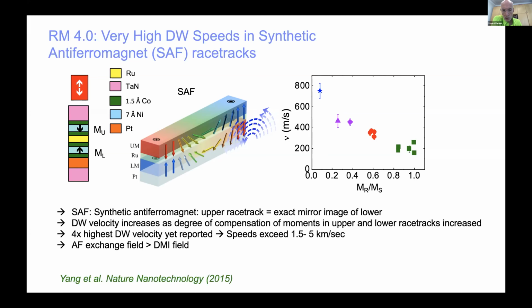ferromagnetic layer. So the cartoon shows you a domain wall. And the point here is that these domain walls, I didn't mention, this platinum layer provides another very interesting aspect, which has been discussed before, which is that it gives rise to a Dzyaloshinskii-Moriya interface exchange, a vector exchange. And because of the broken symmetry, it's only one interface. This causes the domain walls to be chiral, as shown in this cartoon, and also causes them to be Néel-like.